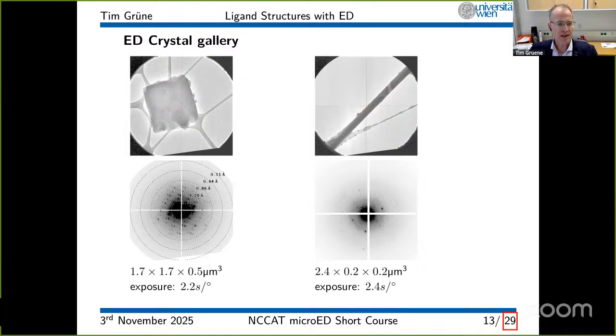One more thing to say, on the left-hand side is a very nice example where you can see the shadow of the lacy carbon. And if you can see through the crystal, it means that the thickness is about right. If your crystal is too thick to see the lacy carbon underneath, in my experience, you start getting strong dynamic effects and the data get worse. And it's very hard to interpret the data, at least with simple programs for data collection.